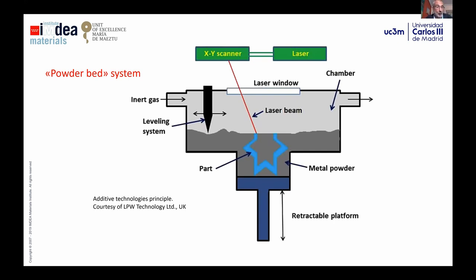One is the so-called powder bed systems, in which we have a bed in which we put the powder, the laser beam acts on the surface, and with this retractable platform, we can grow the part from the top to the bottom. In this case, the main difference regarding the other additive manufacturing methods is that we need, for sure, fully prealloyed powders with very well-controlled microstructure, in order to assure a good melting on the upper part in which we are applying the laser beam.